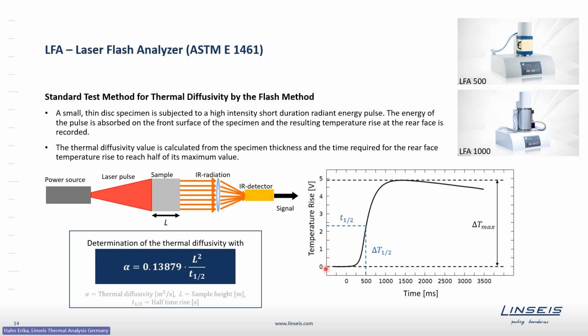Now you first have the baseline, then at time stamp 0, the laser shot or the light shot will be initiated, and then we have a look at the temperature rise with time. Out of this curve, one can then calculate, using some physical mathematical models, the thermal diffusivity according to that formula, where the thermal diffusivity is the product of a constant factor and the sample thickness squared, divided by the so-called half-time rise, which can be seen here, how it is determined. So we first determine the maximum amplitude and divide it by 1/2, and then have the timestamp of the half-time rise.